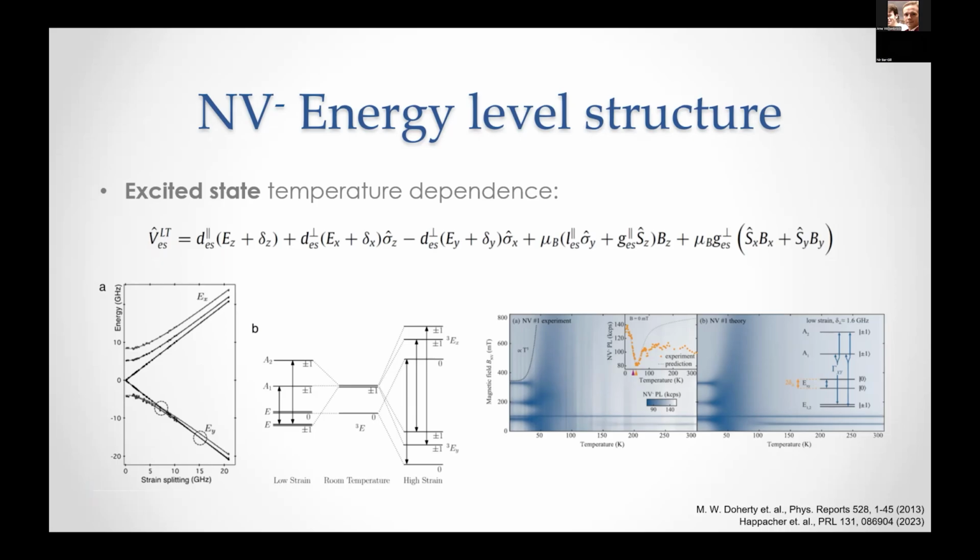Yes. So what's actually happening, you always have 6 levels. That's what you have in there. An orbital doublet and a spin triplet, right? And you can see this here. These are degenerate at 0 strain, so you can see 6 levels. The reason why you see only 3 here is because it's hidden in there that the orbitals are completely mixed. So each one of these spin states is a combination of both orbitals that you just don't see, they average out.